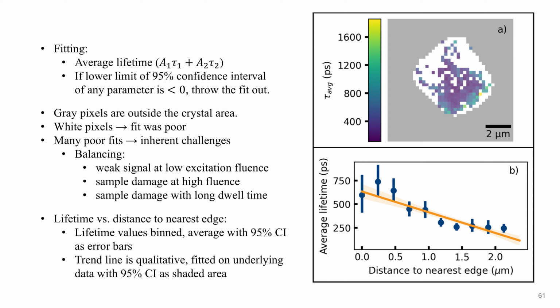White pixels, the fit was poor. There are many poor fits, and there's some, which you'll see in a minute, that are even worse than this. It's just due to the inherent challenges of the measurement procedure, where I had to balance weak signal if I have low excitation fluence, but sample damage if I have high excitation fluence, and finding that balance was difficult. And so some of the measurements, I just had a lot of noise.